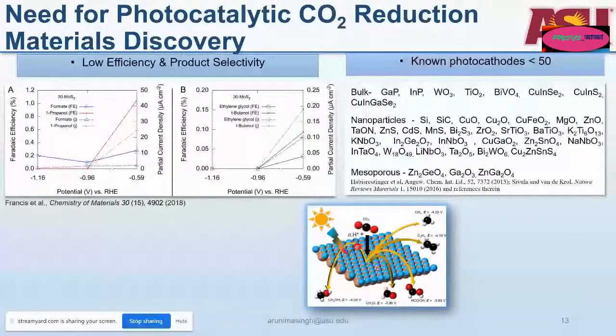The photocatalysts for CO2 reduction known to us have poor efficiencies and product selectivities, which is evident in this figure here, which I've taken from this experimental article. You look at the Faradaic efficiency. You can see it's less than 2%. And you can also see there are several products which are formed when you use MoS2 as a catalyst for CO2 reduction.